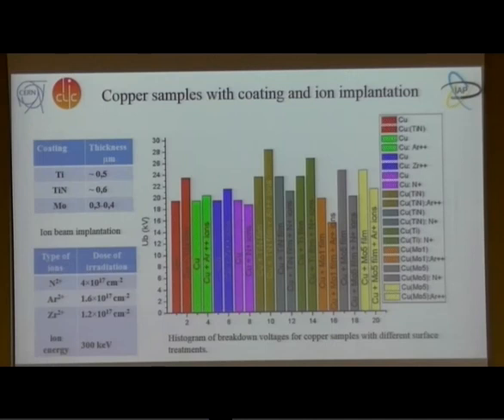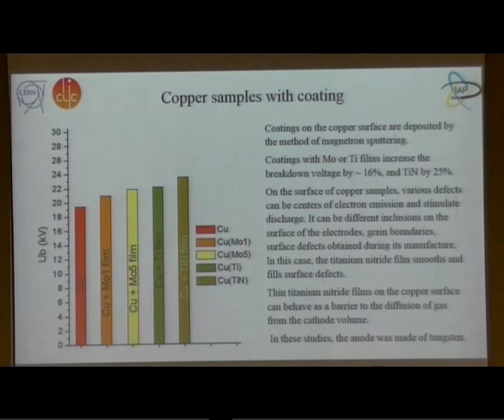In this slide, the total histogram of breakdown voltage is shown for copper samples with different surface treatment: copper plus titanium film, copper plus argon 2+ irradiation, and others. Copper samples with coating.